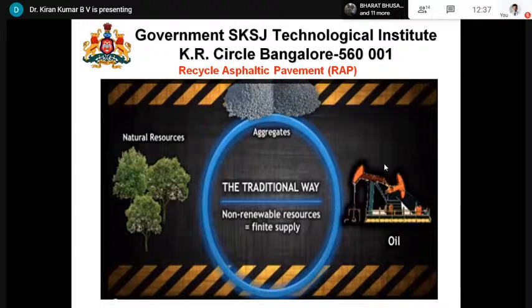Below that, there is a granular layer, based on the base courses, which are basically either WMM, wet mix macadam, or WBM, depending upon the specifications, construction time, and which agency has done it. When we are milling this in conventional recycling of asphaltic pavement, the milling machine has cutters, and those cutters damage the receiving layers also. Again, we need to strengthen the receiving layers and then go for the recycled asphalt over that. That is where our new technology comes into the picture, how we are going to do it.